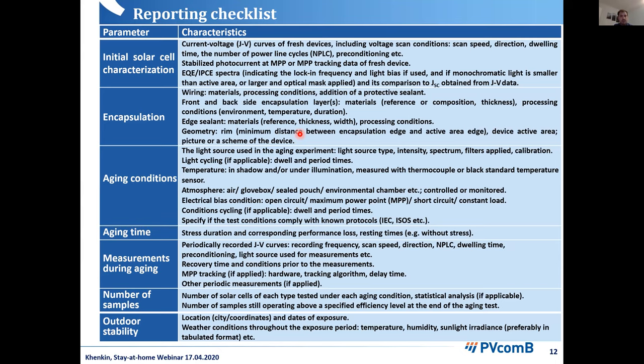In a nutshell, you need to report the initial parameters of your solar cell — the device layout, efficiency, packaging or encapsulation, aging conditions, duration, and the statistics collected across different solar cells. This is where it gets tricky: perovskite solar cells are not particularly known for reproducibility even when produced with the same procedure. Getting statistics is important but equipment-intensive and can be expensive, and not many labs in the world have the capability to do so.